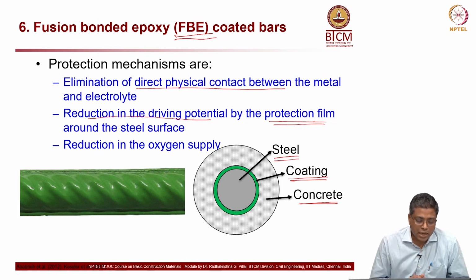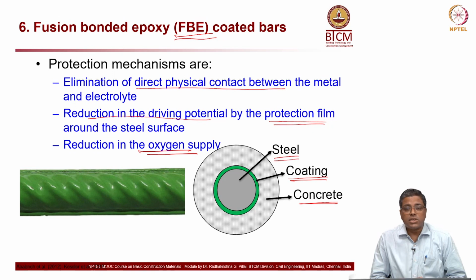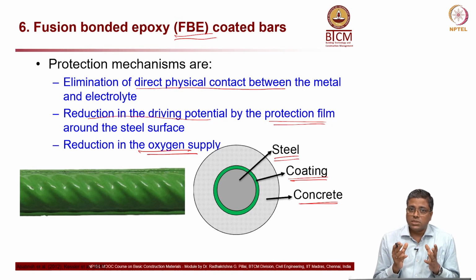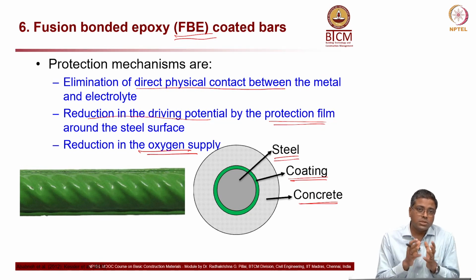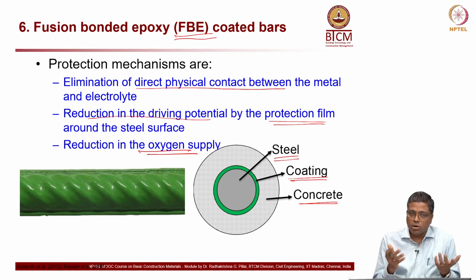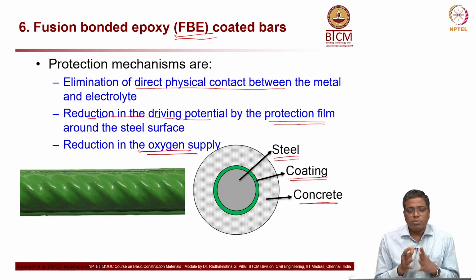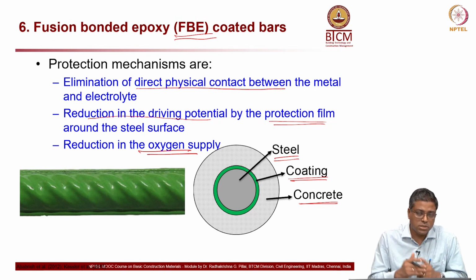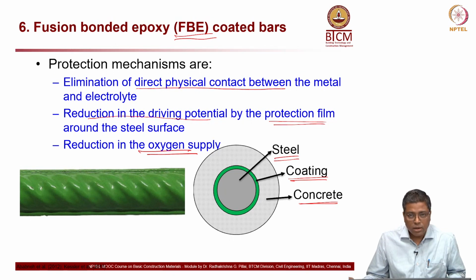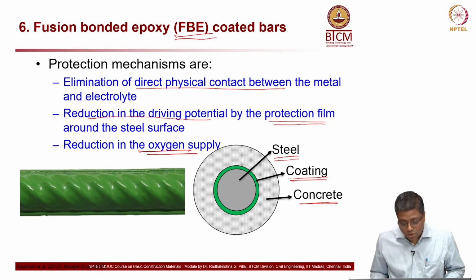So, a mechanical barrier is actually provided, and because of this you also have a reduction in the oxygen supply at the steel surface, because you know very well that oxygen and moisture are essential for the corrosion reactions to happen. Like in the cathodic reaction you have both oxygen and moisture. So, if you can stop either one of them, you cannot have corrosion. So, this epoxy coating provides a physical barrier, it reduces the driving potential, and also it provides a barrier against oxygen. Okay. So, at the steel surface you don't have any oxygen or moisture if you have a good quality epoxy coating.